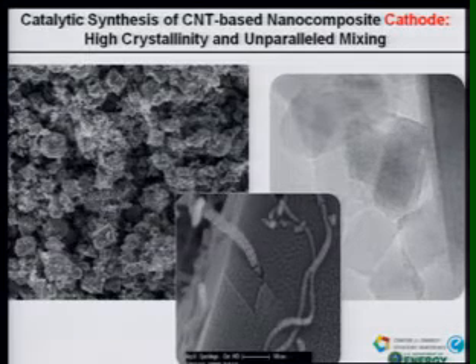Most recently, we have found we can extend this method generically to make high-power cathodes as well. And that, we think, is a breakthrough that will make this commercially viable. I show you here the result of our catalytic synthesis of a unique nanocomposite of highly crystalline, you see the facets, nanocrystalline metal oxide and the carbon nanotubes to make a nanocomposite.